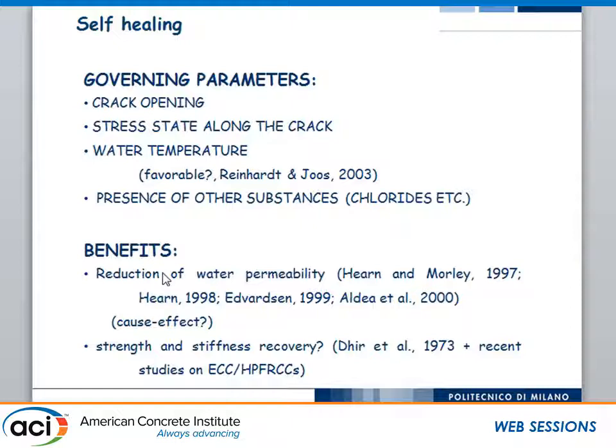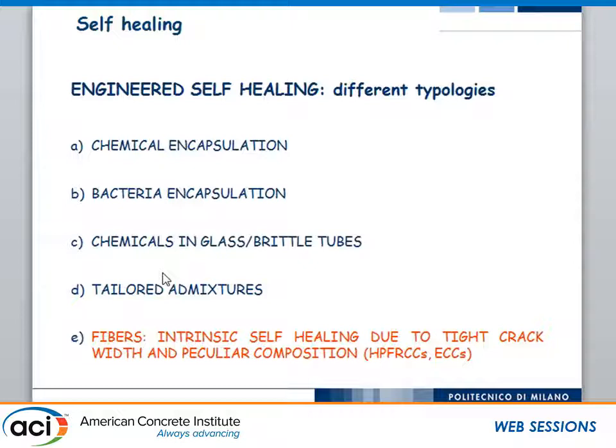So basically, I briefly just list here that among the self-healing methodologies, there are encapsulation of chemicals, bacteria encapsulation, chemicals in brittle glass tubes which break upon cracking, some kind of tailored admixtures, and the synergic effect of fibers which occurs in HPFRCC. The fibers close the crack to a very tight level, and the mix design characteristic guarantees this kind of autonomous self-healing.